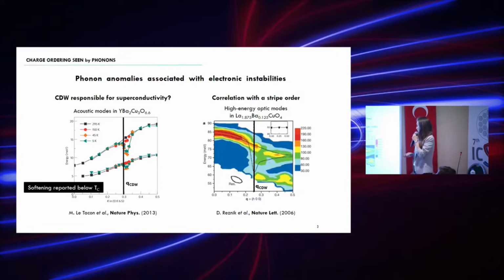However, it was also shown that the electron-phonon coupling in this case is not strong enough to cause the appearance of superconducting pairing. So we knew that the charge density wave order is not responsible by itself for superconductivity. However, it was quite interesting, and people tried to explore the influence of charge density wave order on phonons more thoroughly. And that's the point where it was also shown that the charge density wave order can cause softening of high-energy optic phonon modes. That was shown for a striped system, lanthanum barium copper oxide, and here we see the softening around QCDW.